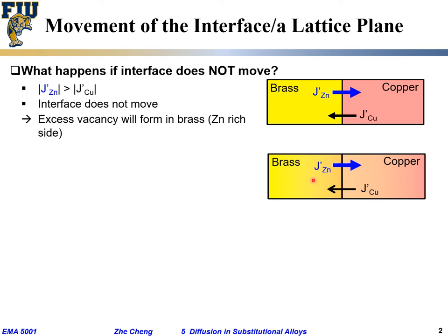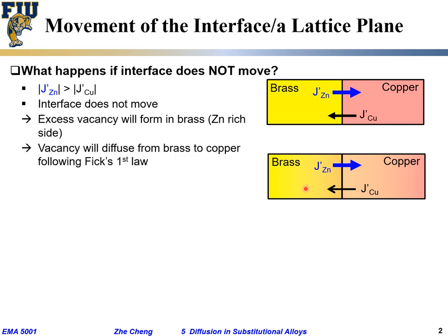On this side, because I have more atoms coming out than atoms coming in, I would have excess vacancy form within the brass, within the zinc-rich side. Okay? I would have a lot of vacancy accumulated here. But if the temperature is high enough, what is going to happen? Will that vacancy sit still? No. And actually, what we learned from before, vacancy diffuses way faster than the self-diffusion or radioactive tracer. Any excess vacancy would quickly diffuse to the section that has lower vacancy concentration. The vacancy will diffuse from brass to copper, also following Fick's law.